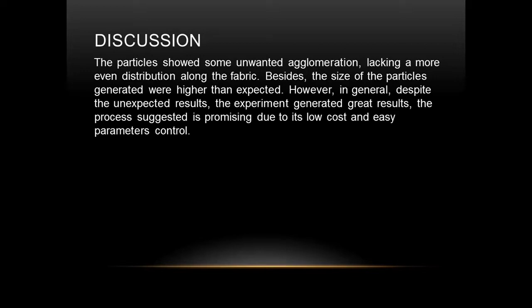To solve such a problem, some dispersing surfactants can be tested, as done by the researchers at King Saud University in Saudi Arabia, adding alpha, beta, and gamma cyclodextrins into the fabrication of the copper particles to avoid agglomeration, thus decreasing the size and improving the spread of the material throughout the test surfaces. Another point noted is that the particles deposited over the fabric fibers are mostly microparticles and not nanoparticles, similarly to what experiments of this sort have done in the past. However, we did not find scientific reports indicating that, to be antimicrobial, the particles must be at nanoscale. Therefore, the particle size interference can be analyzed in future studies.